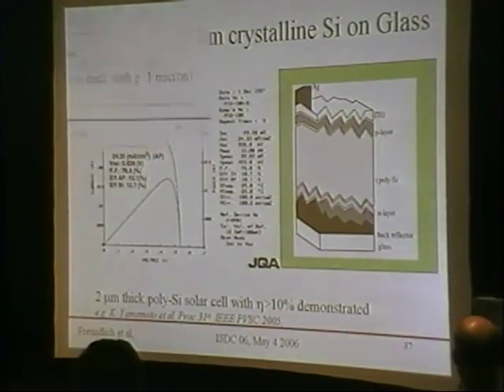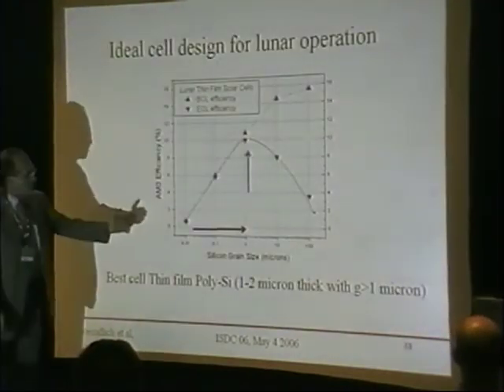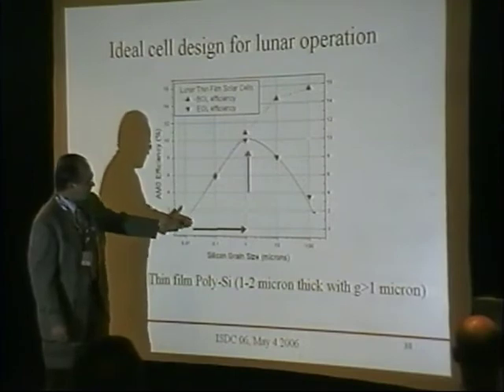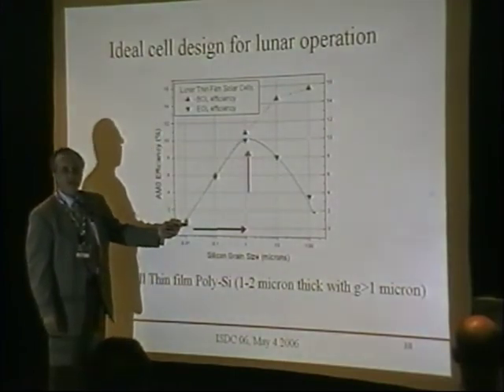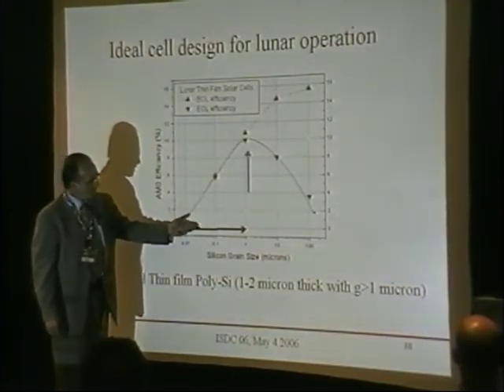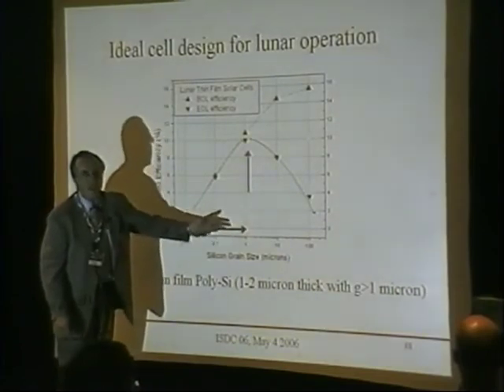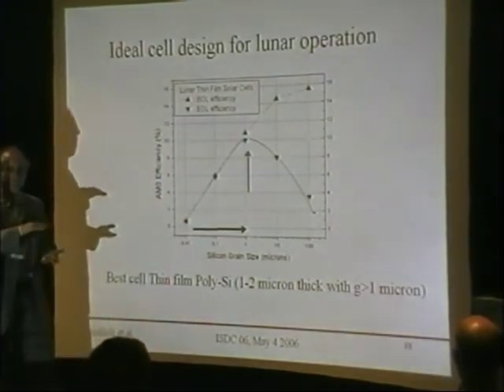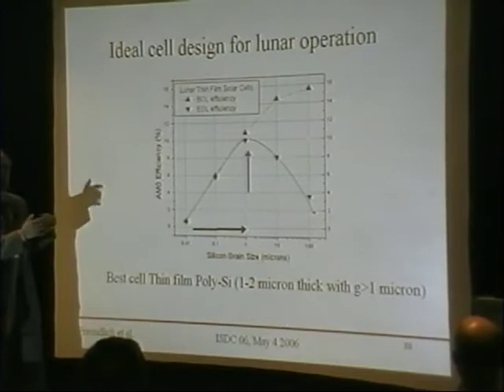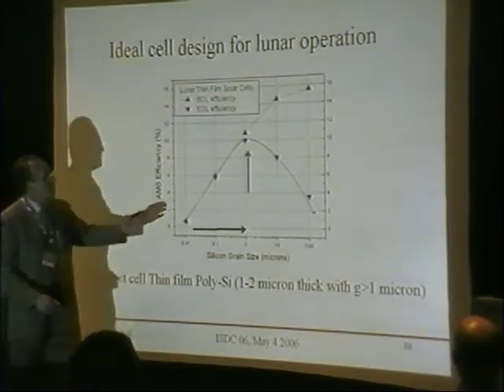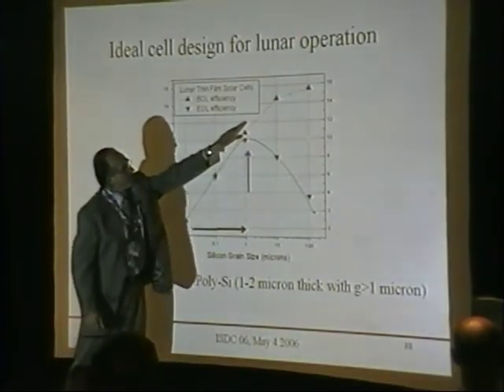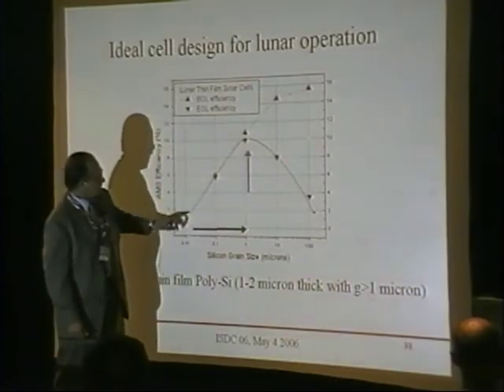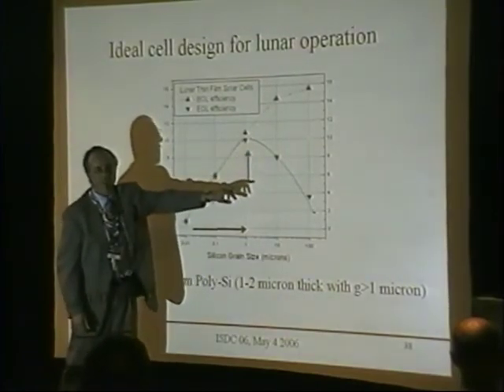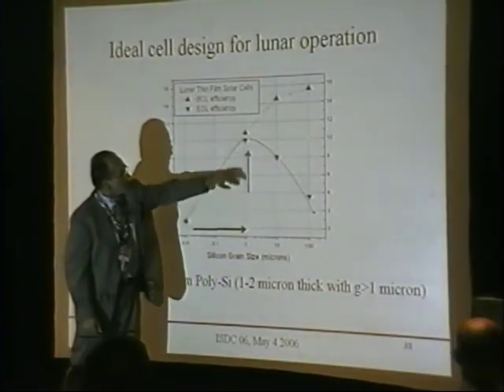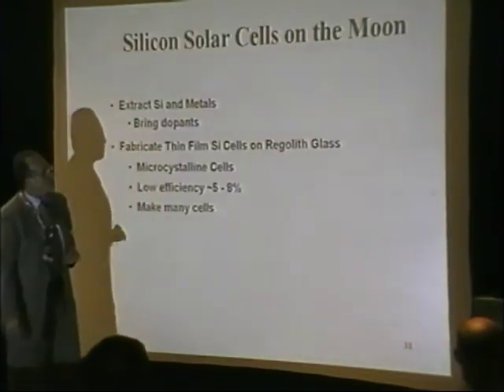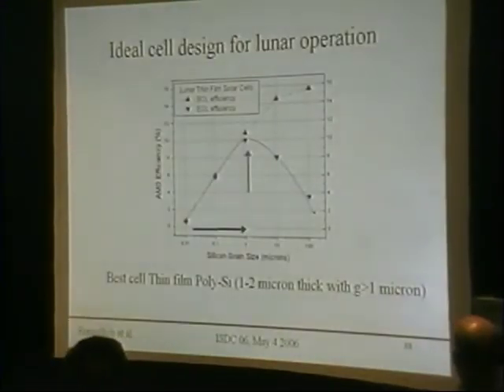Next. Our goal is to improve the efficiency, and that's what we are working on right now. The early cells we made were almost amorphous, very close to here. We're now getting close to the micron, using thermal annealing after the process, and I will show you how it can be done directly on the rover. The beginning-of-life efficiency is the red one here, and green is the end-of-life efficiency you will get after 10 years of operation. One can push that end-of-life efficiency to about 10%. Next.